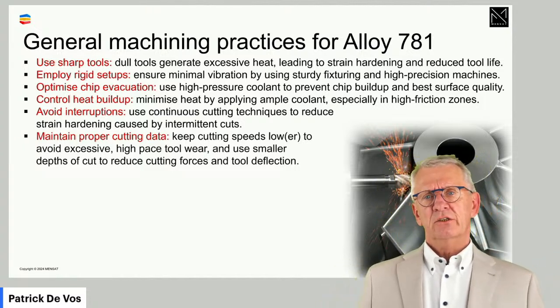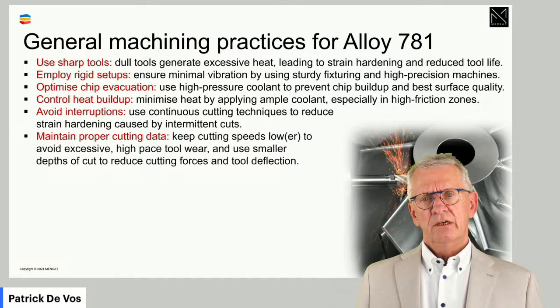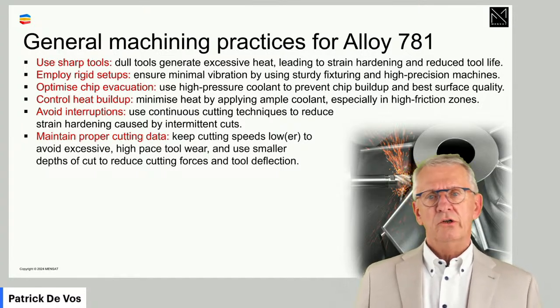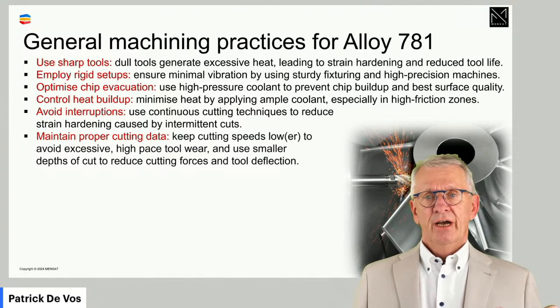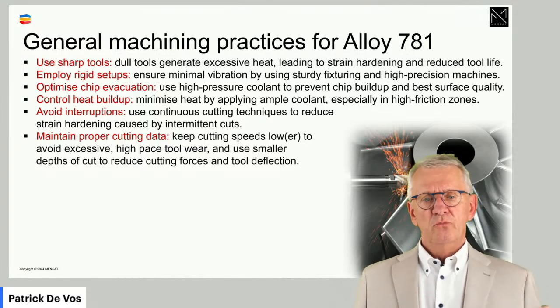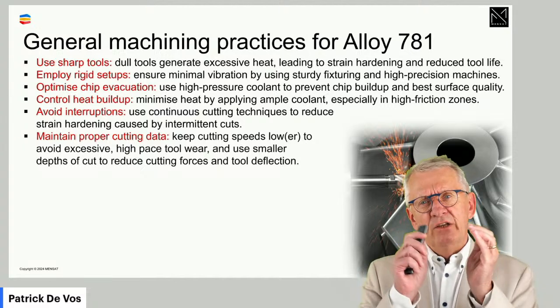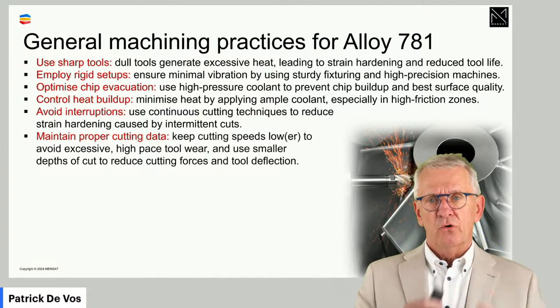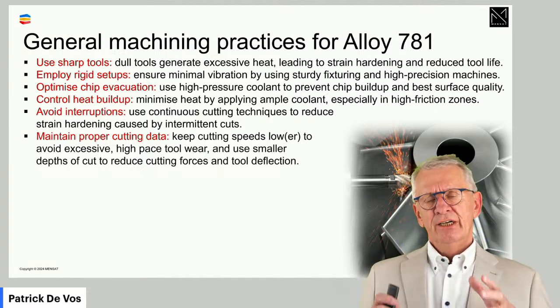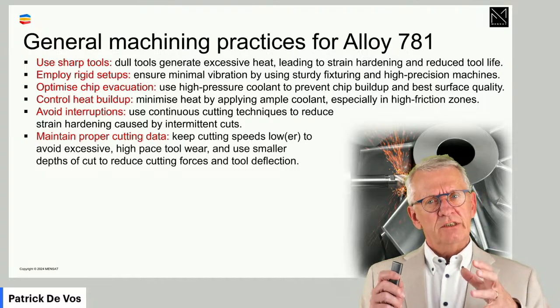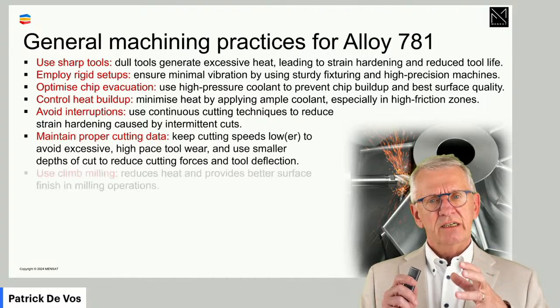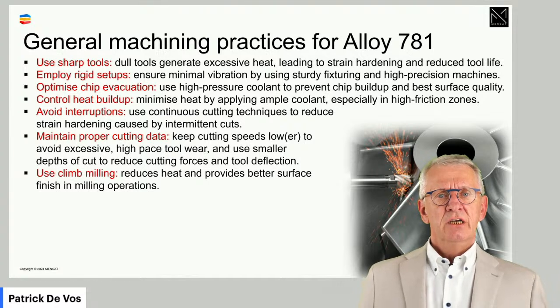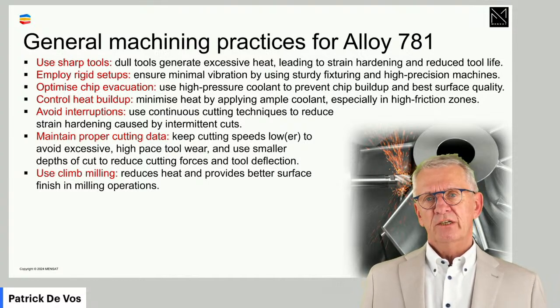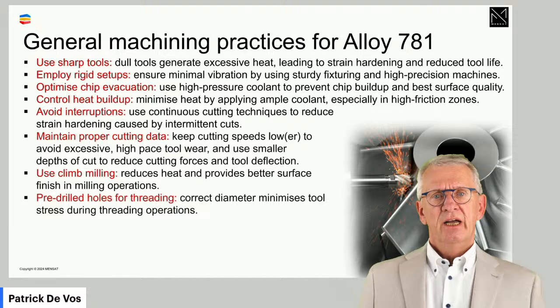Make sure you have the correct cutting conditions. That your cutting speeds are not too high, your feeds are not too low but not too high, your depths of cut should be big but not too big. The window in which you can maneuver, talking about cutting conditions, is rather narrow compared to traditional steel, and you should bear that in mind. Use climb milling, very typical when you have milling applications.